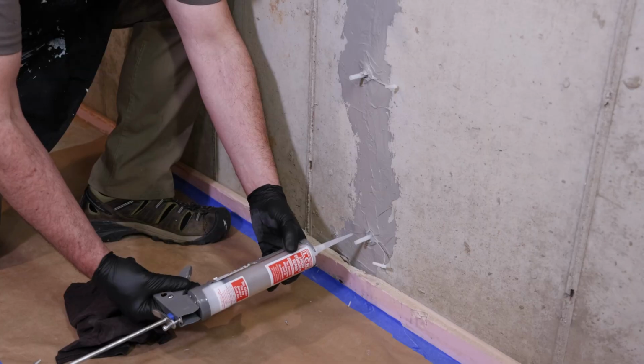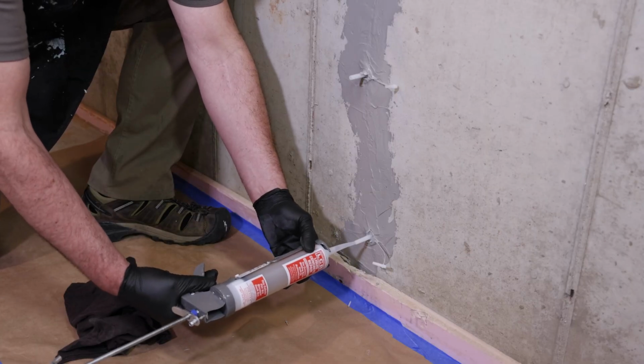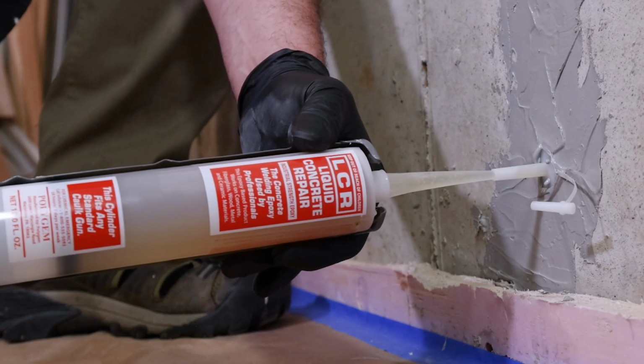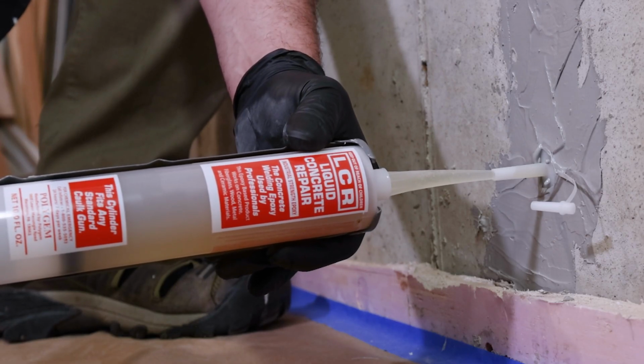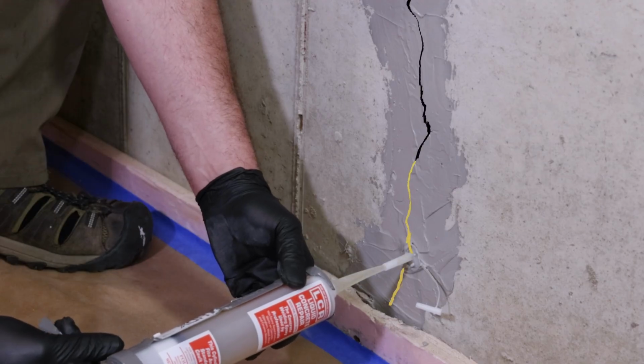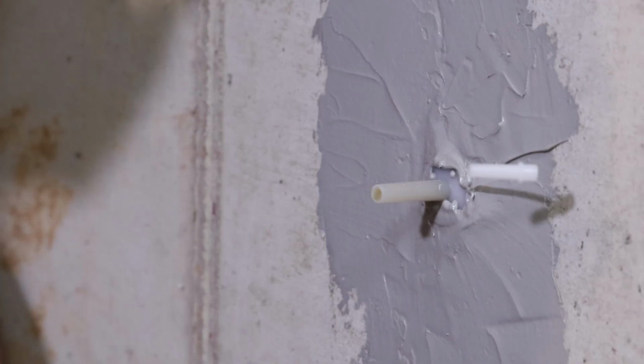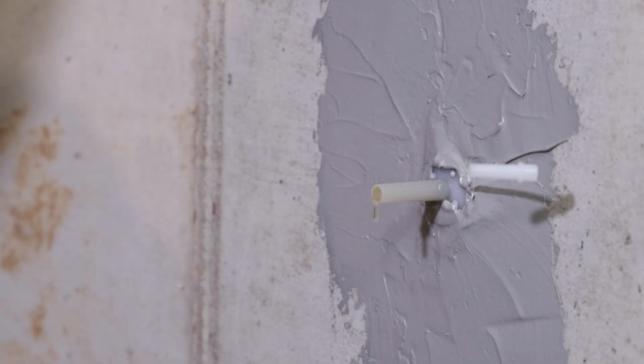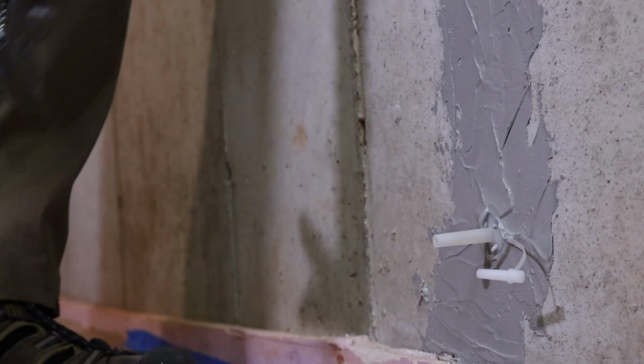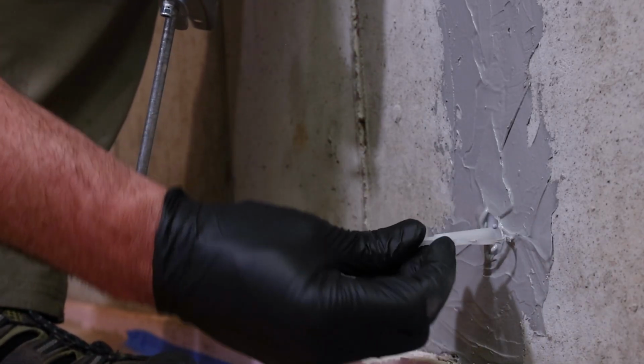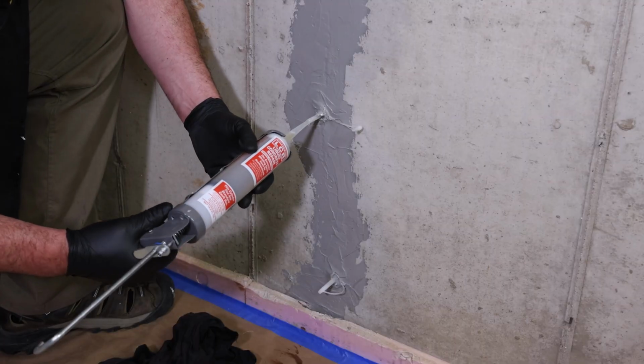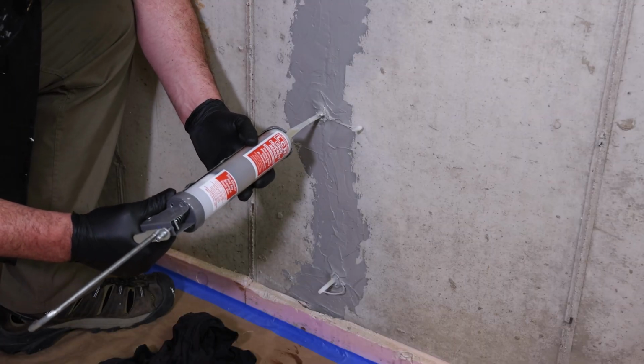It's time to inject the resin. Start at the lowest port, insert the nozzle firmly, and apply steady pressure on the trigger. The resin will start filling the inside of the crack and work its way up. Once resin begins to flow out of the port above, remove the nozzle and cap the filled port. Move to the next one and repeat this process until all ports are filled.